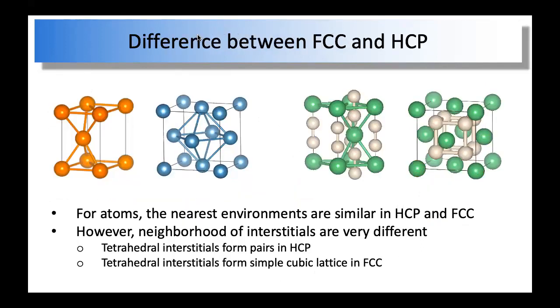Okay. If you look at the differences between the FCC and HCP structures, they're both close packed, and for each atom they all have 12 neighbors. So they are not different topologically. The local environment is very similar for the two. However, if you look at the interstitial sites and their local environment, they are very different.